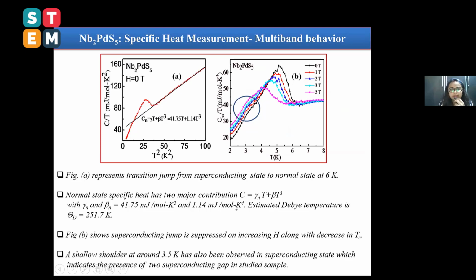After that, we did specific heat measurement to check whether it is a multiband or single band superconductor. Figure A shows that there is a transition jump from the superconducting state to the normal state at 6 Kelvin. The normal specific heat has two major contributions, gamma T plus beta T cubed, that is electronic and phononic contribution. Figure B shows the electronic specific heat versus temperature plot. Here you can clearly see that with increasing magnetic field, the transition jump decreases.